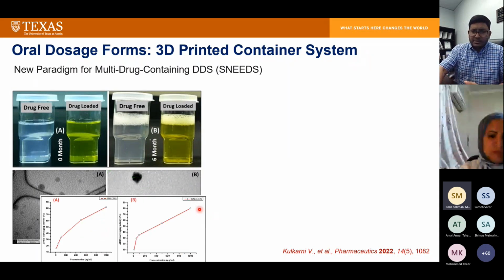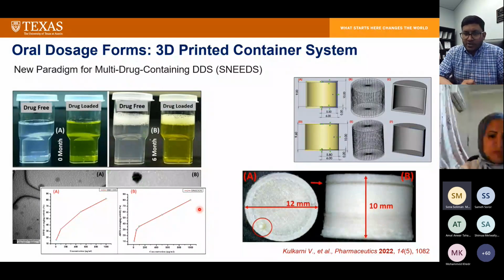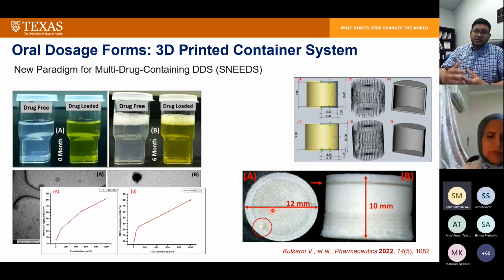So we designed these container platforms where the shell is quite intact. There were no holes or apertures. We only included one aperture of interest over here so that the drug can be released through this aperture once it goes into the intestine. We loaded multiple drug-containing SNEEDS formulations. Here we used two different drugs: one is curcumin, which is a poorly water soluble drug, and the second one was lansoprazole, which is a PPI that is highly unstable in acidic conditions.